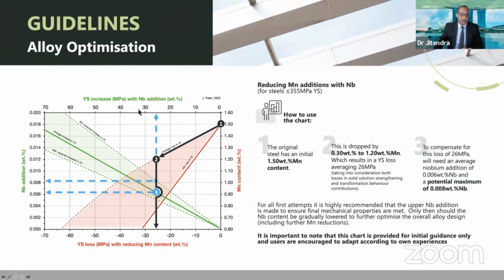In order to get the same strength, we go to the top here, which is the niobium addition, and we read down, and then we intersect the green area here, which is the strengthening contribution from niobium. It then tells us that typically we would need to add about 60 to 80 ppm. What we're saying is you really need to look at around 80 ppm, because from a steelmaking point of view, reaching very, very low levels on a consistent basis is known to be challenging. But around 80 ppm, we believe, is about the right mark to substitute about 0.25 to 0.3 manganese content. And what we found is that as you go to flat products, this is extended more, and as you go towards longer product sections and bars, that is slightly less. This is only due to the processing side of steelmaking itself.